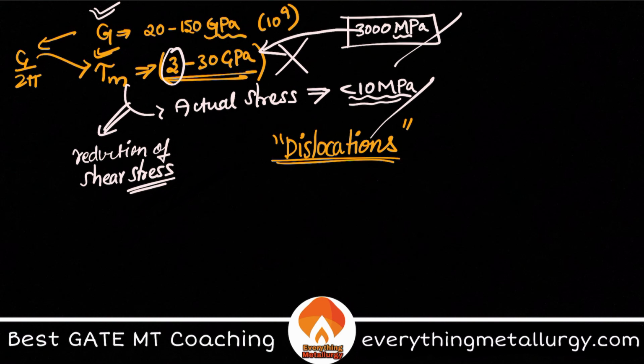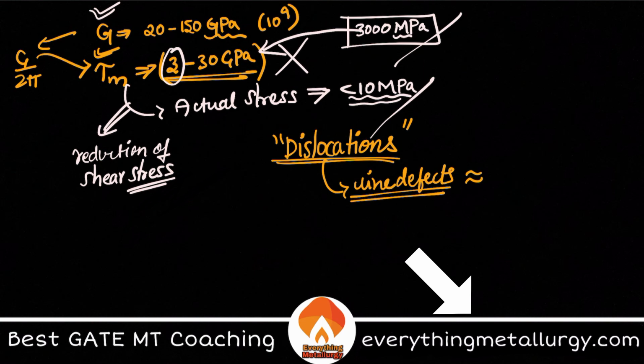That means there are dislocations, line defects, present inside my material which help my material undergo plastic deformation at very, very low values compared to the theoretical values. And this was developed even before looking at the atoms, correct? So dislocations are line defects. Of course, we have had a brief study about dislocations, but line defects are something which are responsible for slip.